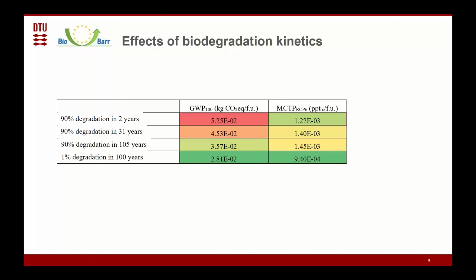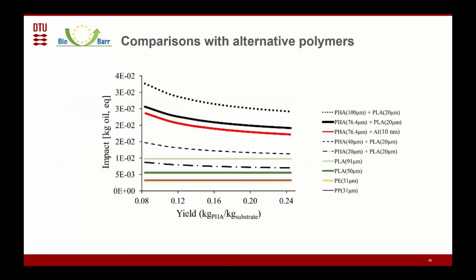For comparison with the new indicator, the climate tipping point potentials, we see that biodegradable polymers actually perform better than those which have higher stability. And there is a reason for that. For these intermediately stable polymers, most of the greenhouse gases from landfilling will be emitted close to the point in time when the probability of crossing projected tipping points is the largest. So there is some added value from using alternative metrics.